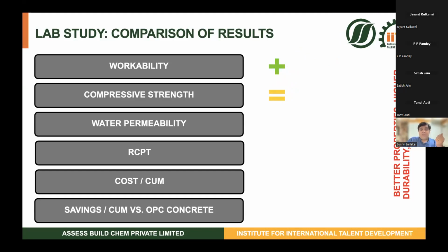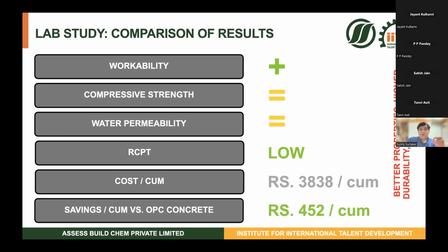When we took a look at the compressive strength, the 100% OPC mixes and the ones with almost half the amount of OPC and the balance GGBFS had almost the same compressive strength. They're very comparable. The water permeability results were slightly better. Where it really won was the RCPT test: as opposed to a medium value for conventional concrete, with the GGBFS concrete it came down to low. And the cost per cubic meter, that was where we were truly astounded, because we saw a savings of almost 450 rupees per cubic meter of concrete with the new mix design.